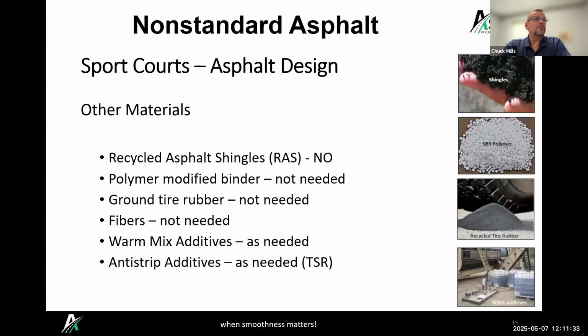Other materials, when we're talking about sports courts, recycled shingles: no, it's not recommended to use those. That can really stiffen up that binder. And when we're designing sport courts, we're not designing them for loads or repeated loads, and we don't worry about rutting. We worry about cracking. So we want to use a very durable mix, and asphalt shingles usually make a stiffer mix. It's not necessary to use polymer modified binders. Not really necessary to use ground tire rubber or fibers.